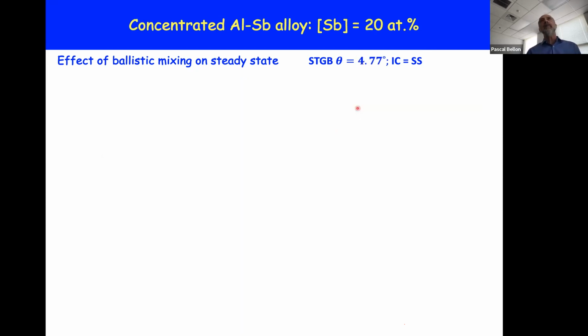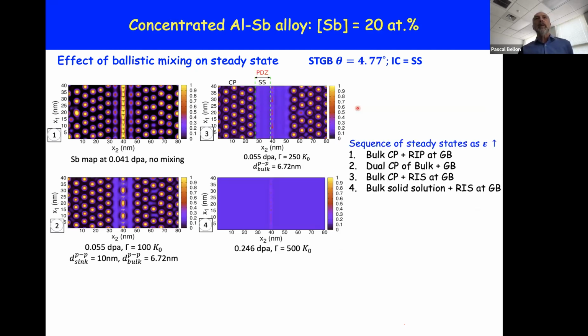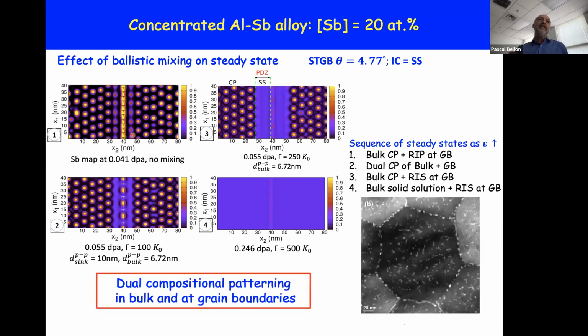This was in a dilute system. We've done this also in a concentrated system, in a case at 20% antimony, where there is also patterning in the bulk as well as the grain boundary. In some ways, the phase-field model suggests that we can get dual compositional patterning, where we have larger precipitates along the grain boundary, smaller precipitates in the bulk, and a precipitate-denuded zone at the interface between the two. We argue that in many ways it seems to mimic the microstructure that I showed you earlier. There's still ongoing work to do a more quantitative comparison with the experiments.